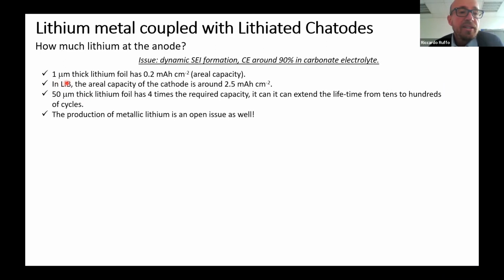So considering that 1 micrometer thick lithium foil has an area capacity of about 0.2 milliampere hour per centimeter square, the area capacity of the cathode is about 10 times that. So right now we want to use 50 micrometer thick lithium foil with 4 times the required capacity in order to extend the lifetime from tens to hundreds of cycles, based on calculation on the efficiency of the process.